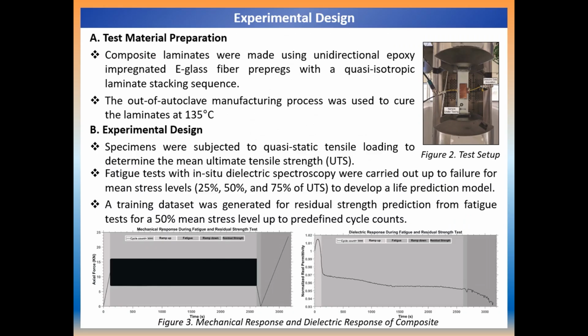In this study, composite laminates were fabricated using unidirectional epoxy e-glass fiber prepregs. Initially randomly selected specimens were subjected to quasi-static tensile loading to determine the sample mean ultimate tensile strength. Then initial fatigue tests and residual strength tests were performed to determine respective 95% confidence intervals of cycles to failure for each mean stress level and residual strength at different cycle counts, along with in situ dielectric spectroscopy data acquisition.